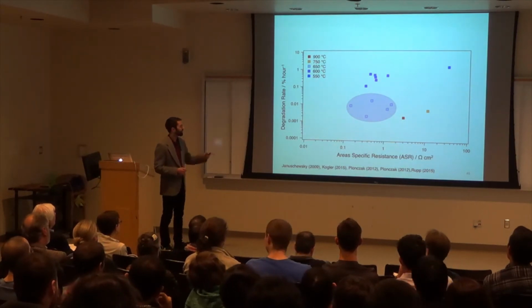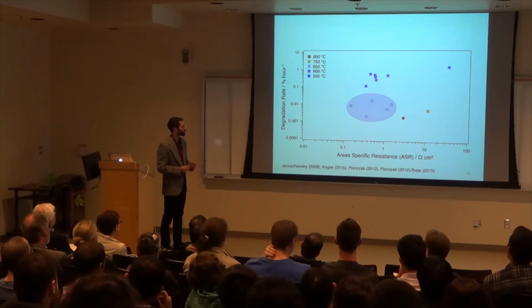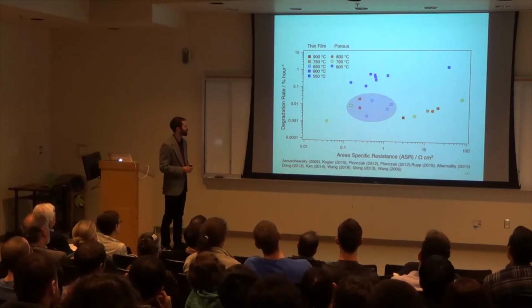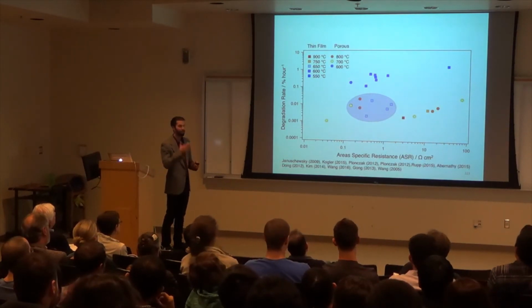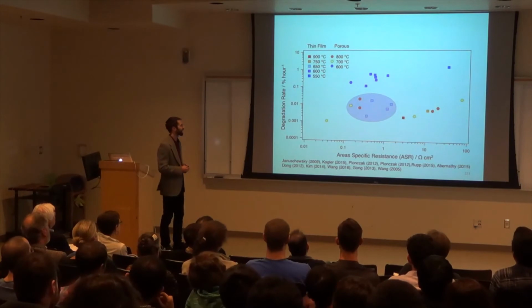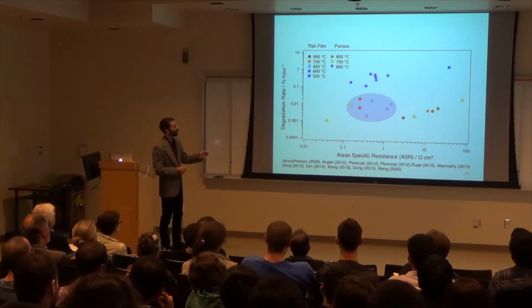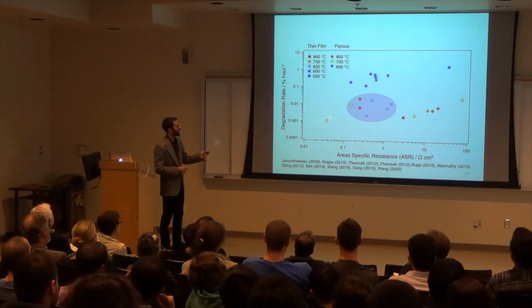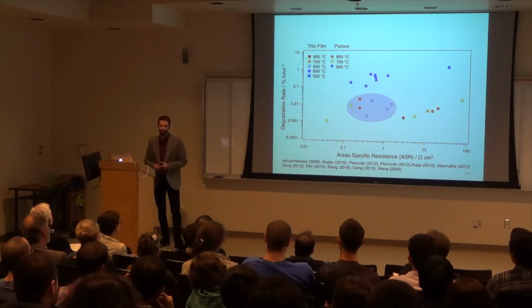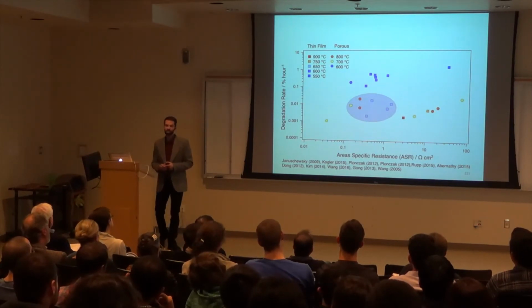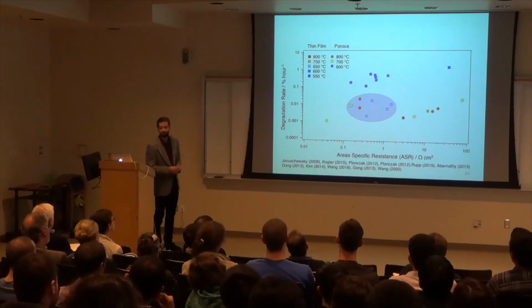And when we put our literature results of all different material systems on here that are brave enough to put their degradation rates and their catalytic activity, we see that a lot of them are operating at high temperature, and we have this outlier here, which is one of the most active catalysts. It is still somewhat unstable, but doing pretty well.